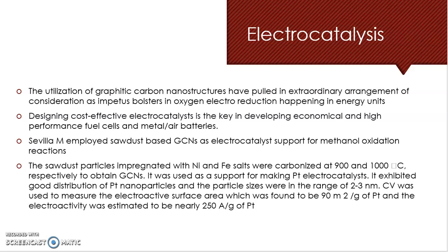Sevilla M employed sawdust-based graphitic carbon nanostructures as electrocatalyst support for methanol oxidation reactions. The sawdust particles impregnated with Ni and Fe salts were carbonized at 900 and 1000 degrees centigrade respectively to obtain GCNs, which is graphitic carbon nanostructures. It was used as a support for making platinum electrocatalyst. It exhibited good distribution of platinum nanoparticles and the particle sizes were in the range of 2 to 3 nanometers.